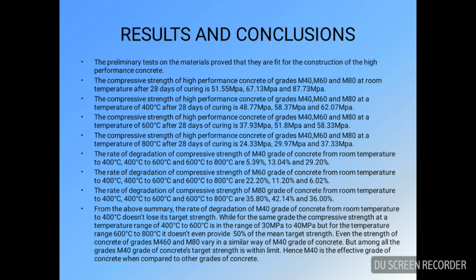So from the above summary, M40 grade of concrete from room temperature to 400 degrees Celsius doesn't lose its target strength, while for the other grades the compressive strength had a change in the range from 30 to 40. For 600 to 800 degrees Celsius, it doesn't even provide us 50% of the mean target strength. The other grades, M60 and M80, behave in a similar way, but among all the grades M40 is within the limit. Hence M40 is an effective grade of concrete when compared to other grades of concrete.